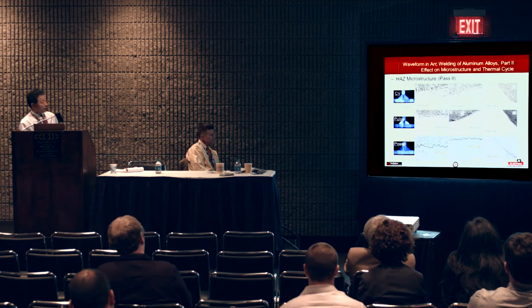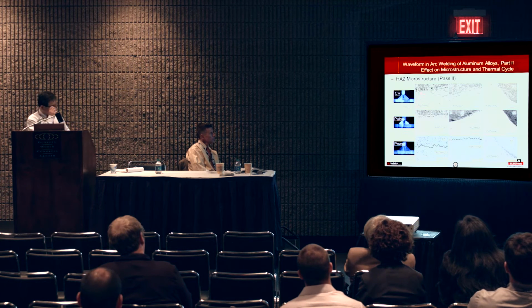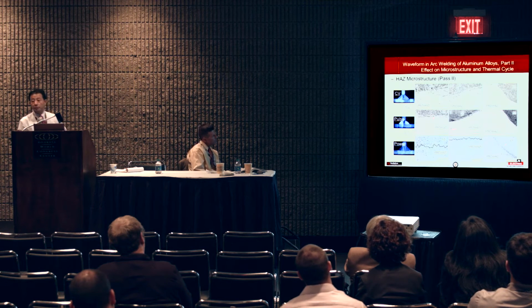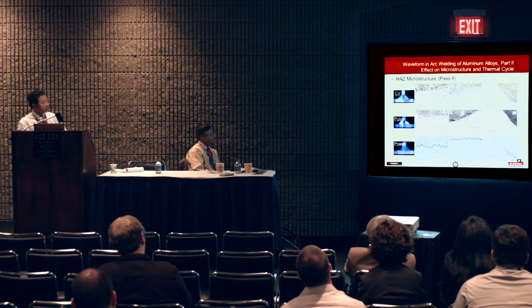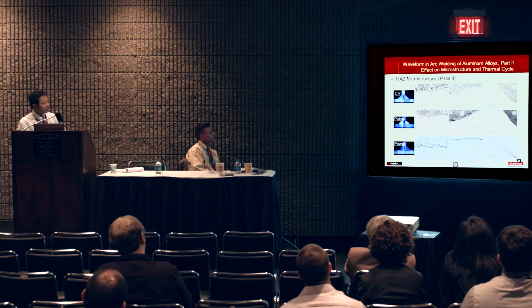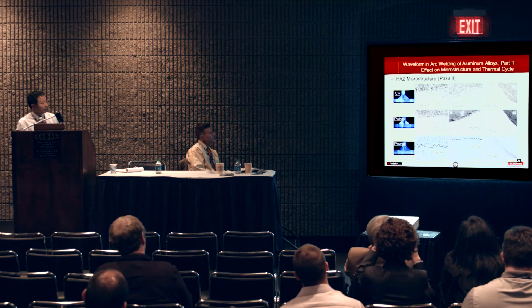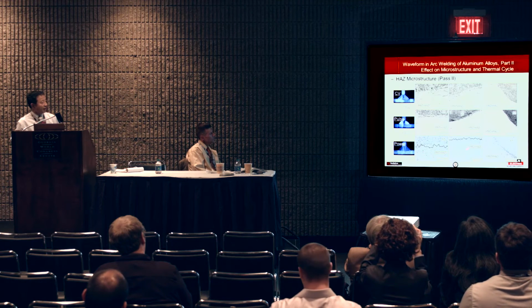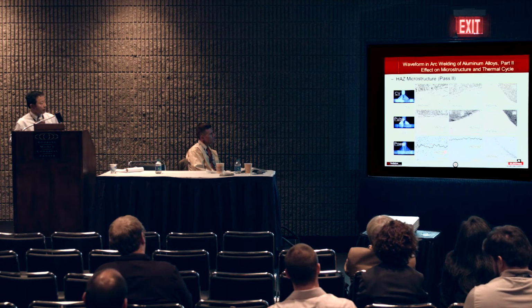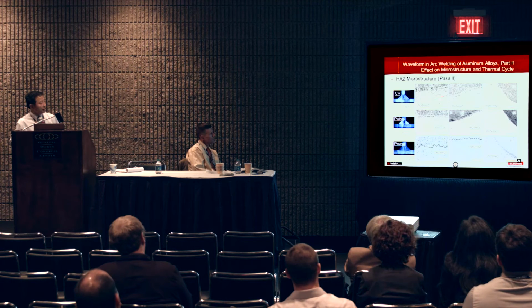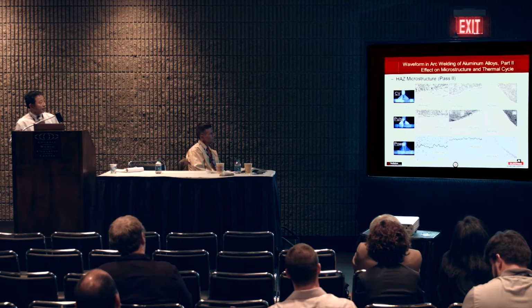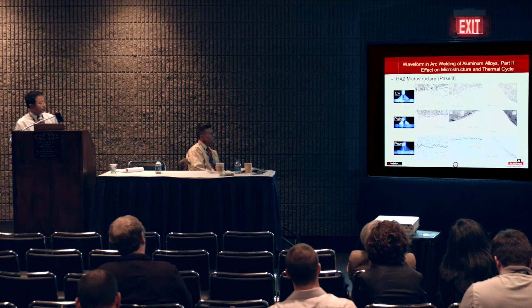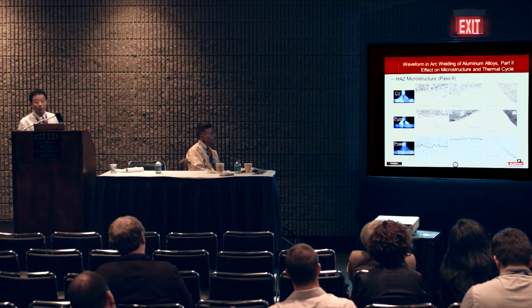And I got the same observation evidence with my pass two, which is the other side of my fillet joint. Repeat the same result. So you can see very big grain size with my CV and pulse mode, but very fine grain size with my power mode. And you see some liquation at the grain boundary with my CV, a little bit with pulse mode, but almost nothing with my power mode.